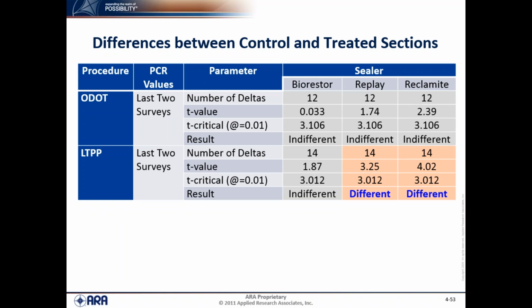Here, all we did was a paired t-test to look at the PCR for the control and the PCR for the treated sections, to see can we say that there is a statistical difference using a paired t-test between the two. If we use ODOT's distress surveys with their calculated PCRs, this is the t-value and this is t-critical at 99%, or an alpha of 0.01. And you can see that there is no difference between the control and each of the individual sealers. If we look at the LTPP, though, we now start seeing a little bit of difference